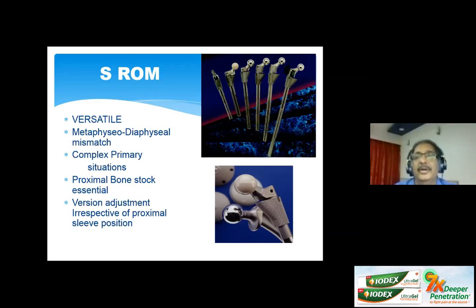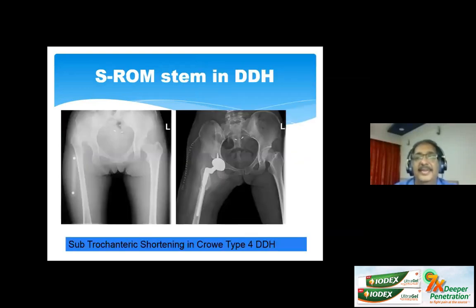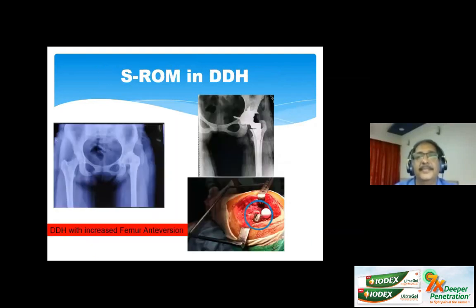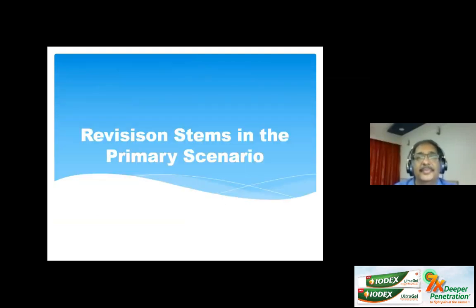Version adjustment is possible irrespective of proximal sleeve position. This is again an important scenario in patients with childhood pathologies where there is a malformed femur, excessively anteverted femur, etc. This is a subtrochanteric shortening of another patient in a Crowe type 4 DDH using the S-ROM stem. This lady I showed earlier, the ceramic on ceramic example, we had to use the S-ROM, and she had an excessive femoral anteversion of 55 degrees odd, but with the S-ROM, we could retrovert the stem within the sleeve by about 30 degrees and get a stable combined anteversion.